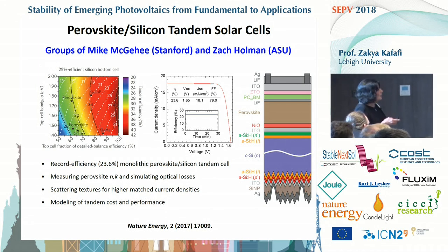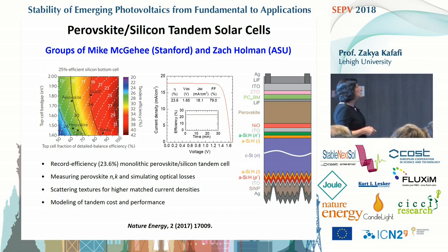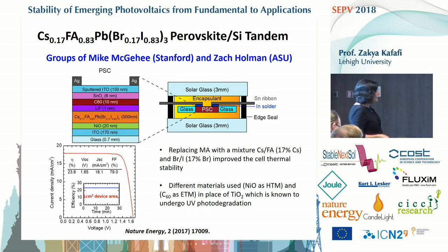Then Zach Holman's group provided a very efficient silicon cell to Mike McGehee, and together they formed a very good perovskite silicon tandem solar cell, and published their work last year in Nature with a record efficiency of 23.6%. They showed that replacing the methyl ammonium with a mixture of cesium and formamidinium, and having a mixture of bromide and iodide, improved the thermal stability of the cell. They used different materials for the hole transport, like nickel oxide, and for electron transport, like C60, in place of titanium oxide, which is known to undergo photo degradation.